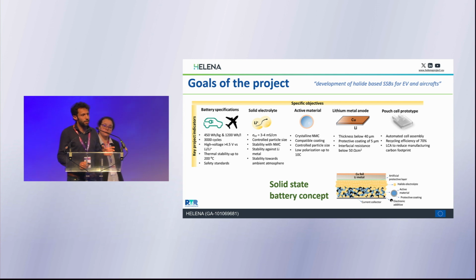In terms of materials, we have KPIs defined for the solid electrolyte. Here we are working with a halide material which exhibits a high ionic conductivity, but there is also a whole work in the project on how to improve the electrochemical properties of this material as the core of the battery cell configuration. So it also has to be stable against the active material and towards the lithium metal anode. There is also development and engineering of the active material. Here we are dealing with high voltage NMC.